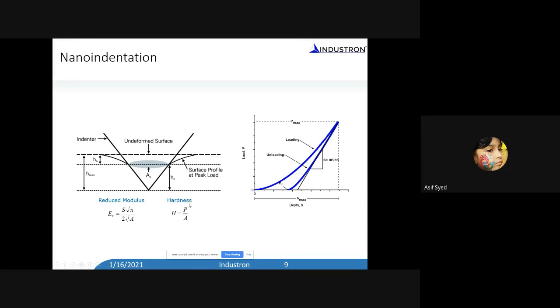Then we can take the same tip, which is basically a diamond tip, and indent on some other material for which you don't know the modulus, but we know for a given depth what the contact area is. From that calibration curve, if you know the stiffness, you can calculate the modulus of the material. This is how we measure the modulus of the material. And if you take the load divided by area, it gives you the hardness. This is how we measure the hardness and modulus of the material. It's as simple as that.